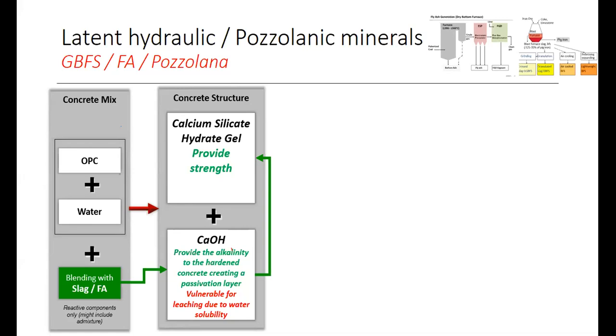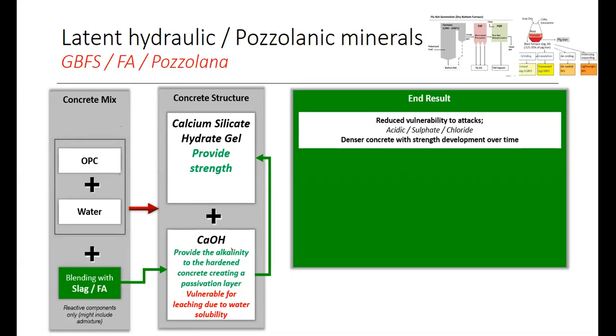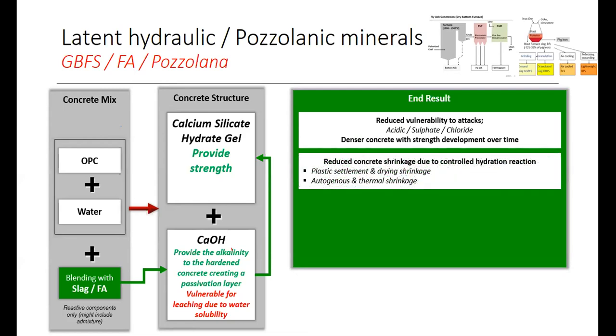So the end result of utilizing those kinds of materials is reduced vulnerability to acidic, sulfate, and chloride attacks, because it's creating a denser concrete with additional strength development over time. This is a positive side.